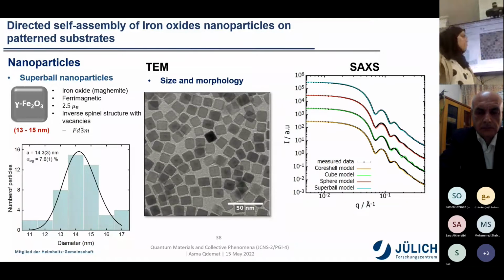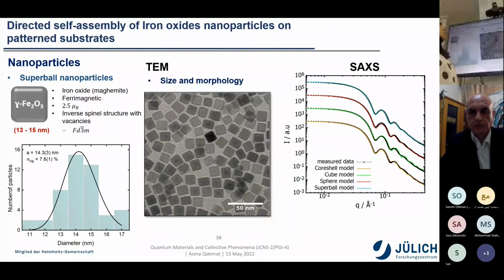Further, to get global or average statistical information about these particles, I performed a small angle X-ray scattering measurement, and here we can see the SAXS curve. From the SAXS curve, I tried to fit it assuming different models: core-shell model, cube model, sphere model, and superball model, in order to get the exact shape of the particle. We can see here the core-shell model, the orange one, which overestimates the first and the second minima.